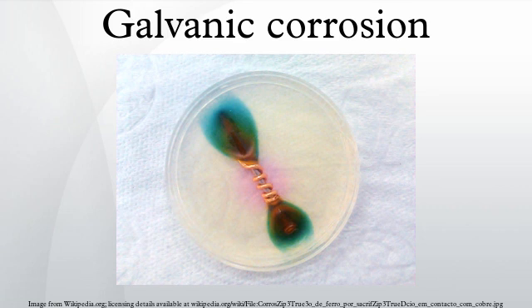Statue of Liberty: a spectacular example of galvanic corrosion occurred in the Statue of Liberty when regular maintenance checks in the 1980s revealed that corrosion had taken place between the outer copper skin and the wrought iron support structure. Although the problem had been anticipated when the structure was built by Gustav Eiffel to Frédéric Bartholdi's design in the 1880s, the insulation layer of shellac between the two metals had failed over time and resulted in rusting of the iron supports. An extensive renovation requiring complete disassembly replaced the original insulation with PTFE, as a precautionary measure for what is considered a national symbol of the United States.